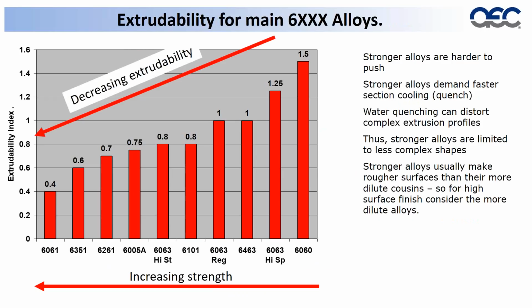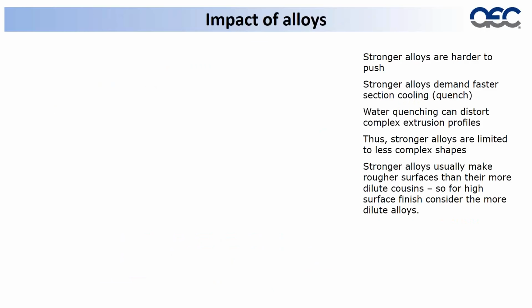The problem is the fast quenching in that water bath causes strong distortions. So the stronger alloys are limited really to less complex shapes. If you want fine screw lugs and long, thin arms and nice things to make architectural shapes, some of these stronger alloys just can't be done because to get the strength, they have to be quenched in water, and quenching them in water will distort the shape. So it's a little bit of a cat chasing its own tail.